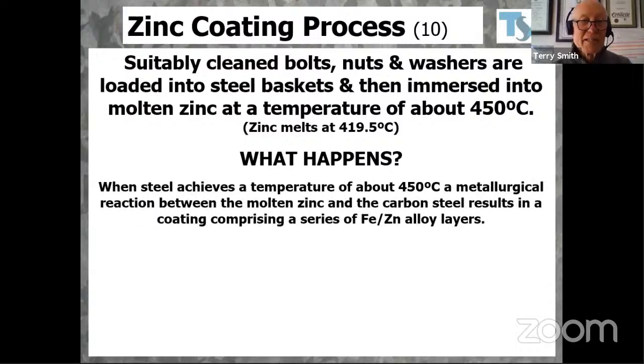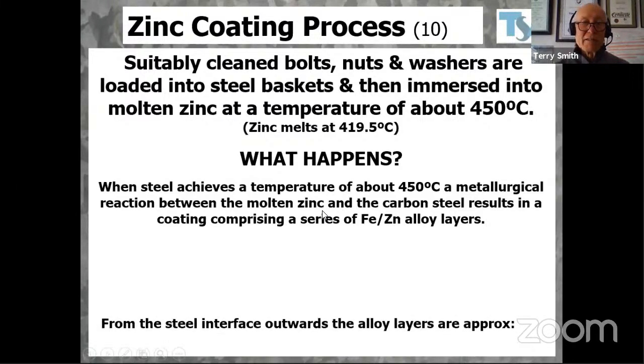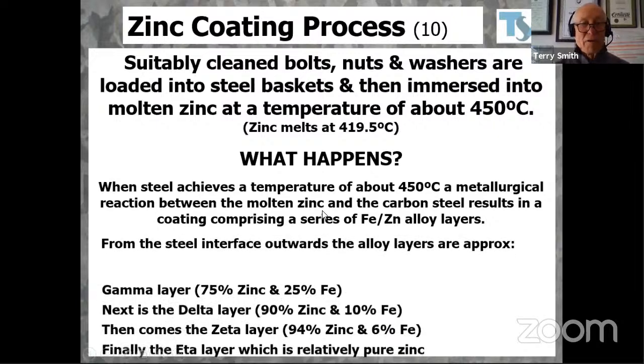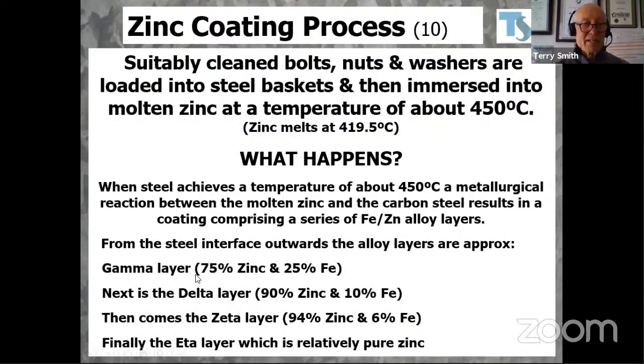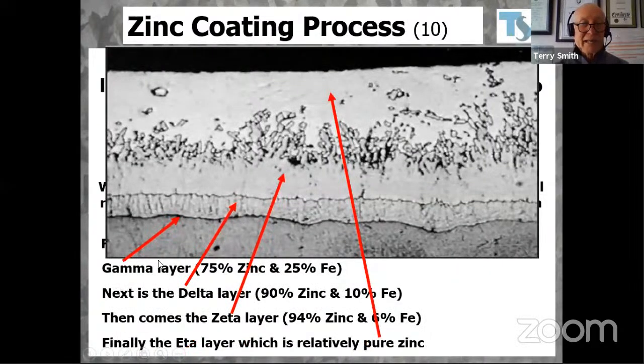What happens? Steel achieves a temperature of about 450. A metallurgical reaction happens between the molten zinc and the carbon steel. And from the steel interface, we have various iron-zinc alloy layers. You'll see in the following slide the gamma layer, which is right adjacent to the steel, the delta layer, the zeta layer, and the eta layer, the outside soft layer.